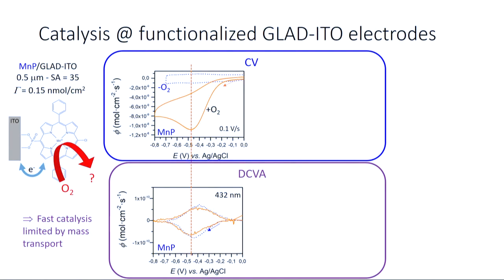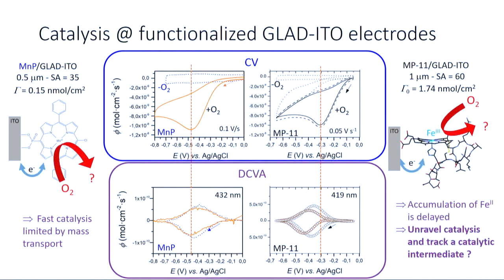And to demonstrate the interest of the technique, I have to move to another redox probe, which is this time microperoxidase 11, which is also immobilized in a glad indium tin oxide electrode. And it's also active toward dioxygen reduction, so you also get a huge current intensity under catalytic turnover conditions. And from the DCVA, where you now follow the accumulation of the iron 2 state of the catalyst in the nanostructured electrode, what you notice is that you now have a delay in the accumulation of the iron 2, and it only starts when the electrode is depleted by dioxygen, so you are limited by mass transport.